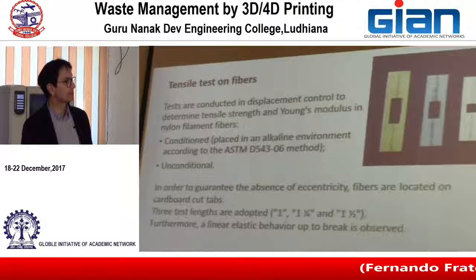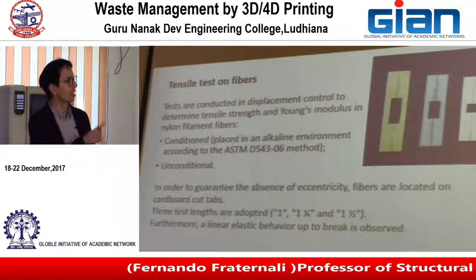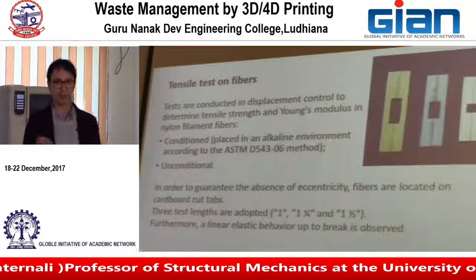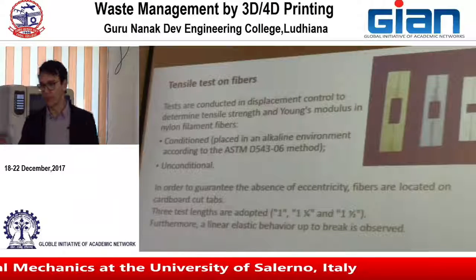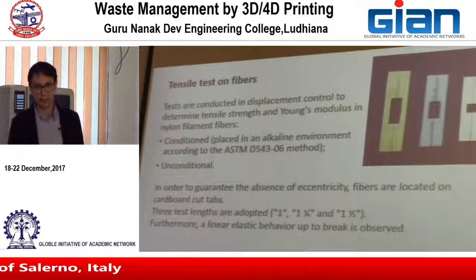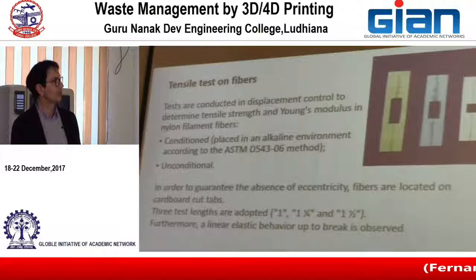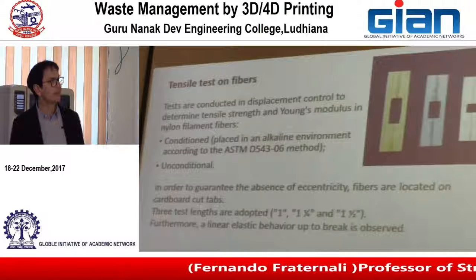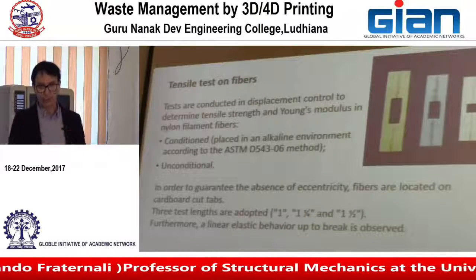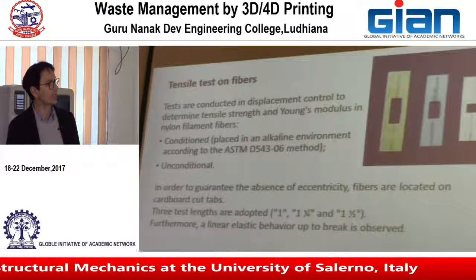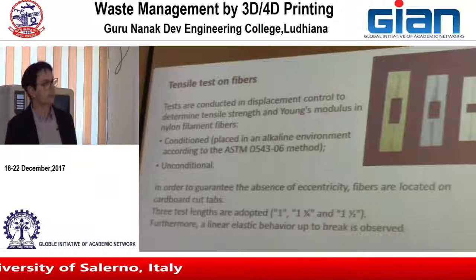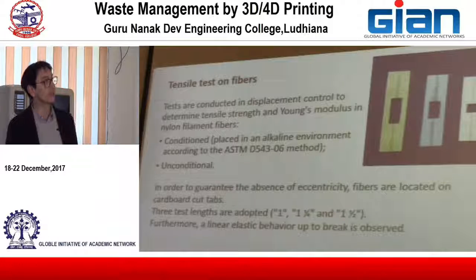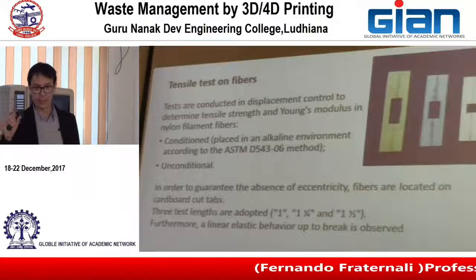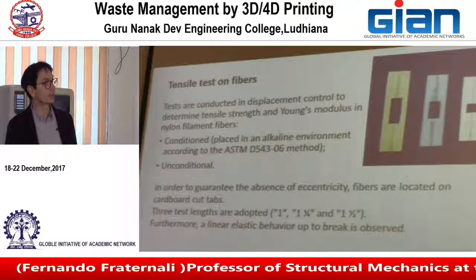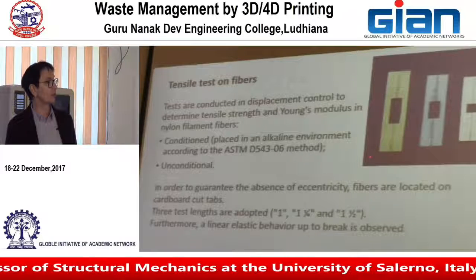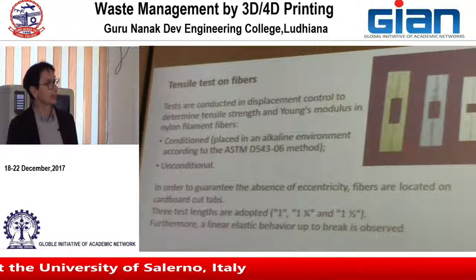For the tensile tests, we adopted some cardboards because there is a problem in measuring the tensile strength that is well known, because in this lab you work with filaments, and so you test mechanically the filaments. So there is a problem in carrying out tensile tests due to gripping problems. So in most cases you have to run tests on specimens with different testing lengths, using cardboard cut tabs.